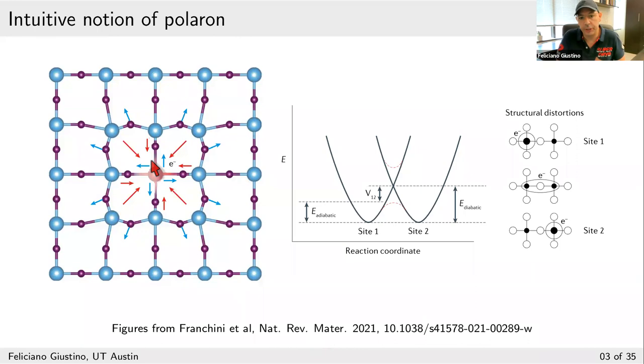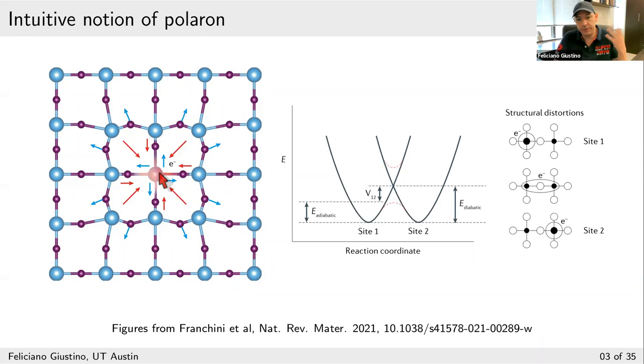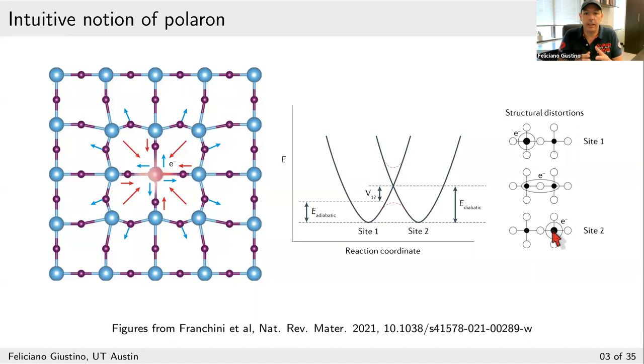The figure on the left shows the intuitive concept of polarons. You have an insulating crystal — maybe a wide-gap semiconductor or an oxide — and you add an extra electron. The electron–lattice interaction is strong enough that the electron will drag some of the atoms around itself, and as a result they may form a localized object. The main consequence is that the electron will be a little bit stuck at this lattice site. If it wants to move to a neighboring site, it will encounter some kind of potential energy barrier. The cartoon on the right shows this process: the electron is localized on site one, overcomes a barrier, and then localizes on site two.